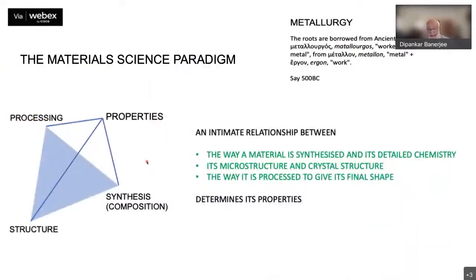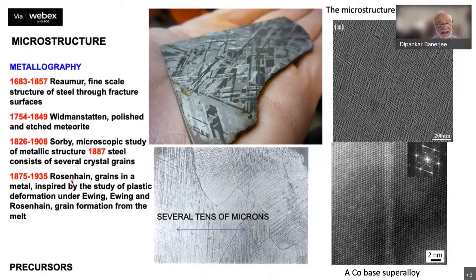I used in the previous slide the idea of structure, and I must talk a little bit about structure, because this is something that most engineers do not recognize as a central feature of materials engineering in this connection between composition, processing, and properties. If you look at a piece of metal, it appears featureless. But somewhere in the 17th or 18th century, we found that if you prepare the surface of a metal properly, you begin to see features in its surface. And we found that these features actually represent grains or crystals which are oriented in different ways.